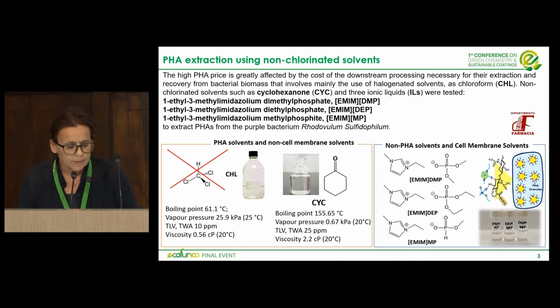For this reason, in this work, we have used cyclohexanone, and in other works, cyclohexanone has been used to extract polyhydroxyalkanoates from bacterial biomass. And you can see the different mechanisms used in this case. In fact, cyclohexanone, like chloroform, solubilizes the PHAs, but not the non-PHA cell matter. On the other hand, the ionic liquids have the potential to solubilize lipids and proteins, the main compounds of the cell membrane of the bacterium, but they are not PHA solvents.